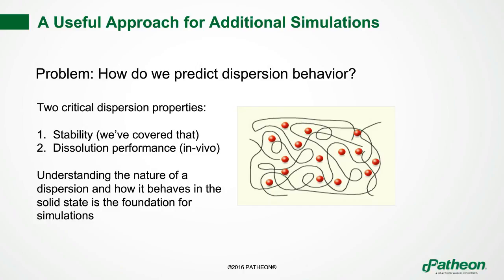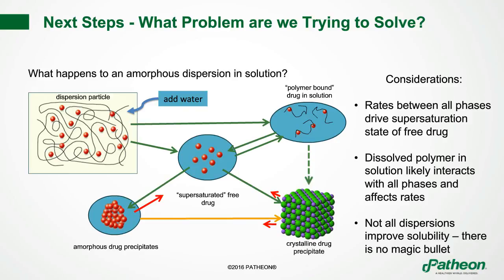But when you think about the dissolution of a drug in a dispersion, this is what's actually happening. Got your dispersion particle, which you see here in the yellow box with the red balls in it and the squiggly lines, the spaghetti and meatballs picture of a dispersion. You add water to that, and what happens is you're going to release polymer into the water as well as drug bound to the polymer. So you're going to create some species that are drug bound to polymer in solution. You're going to create some supersaturated free drug in the middle, and that's what you ultimately care about, is the degree and the extent to which you have supersaturation.